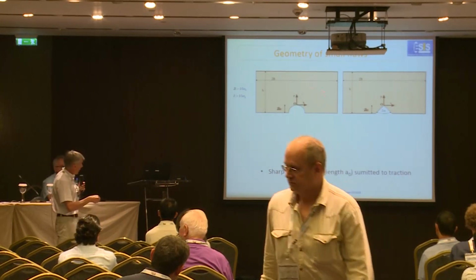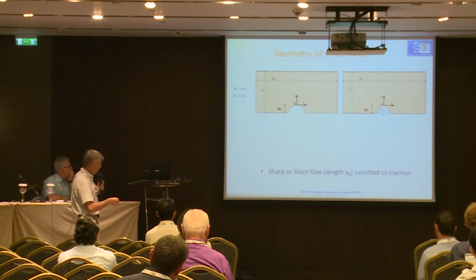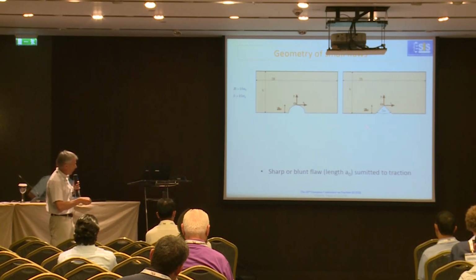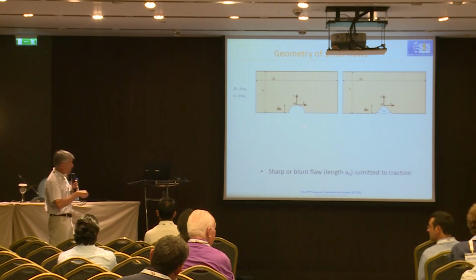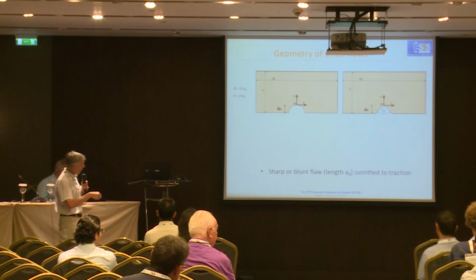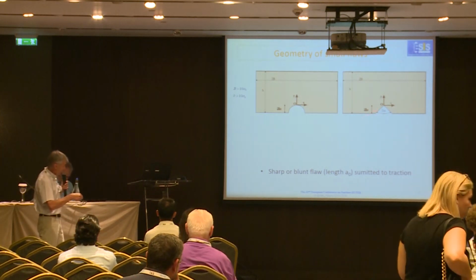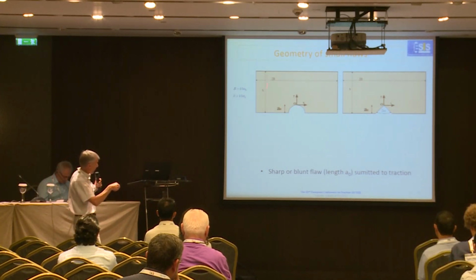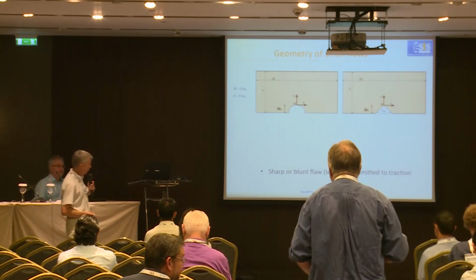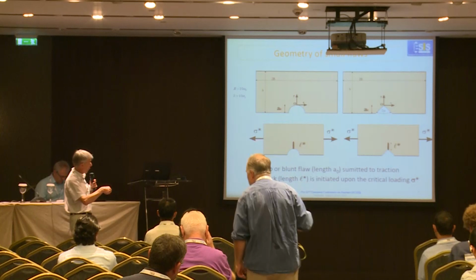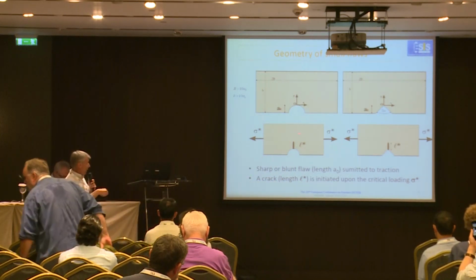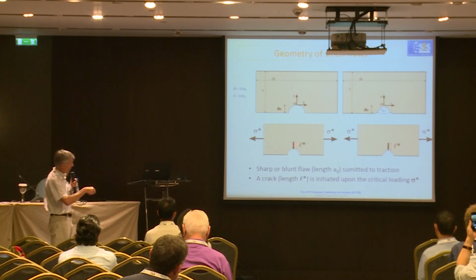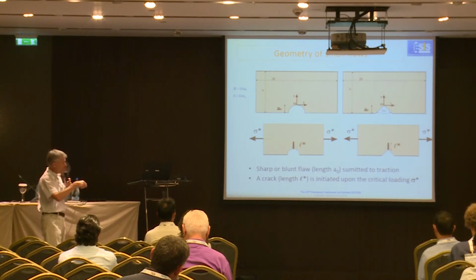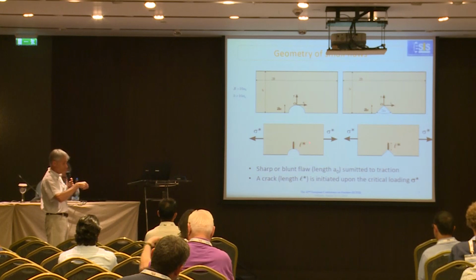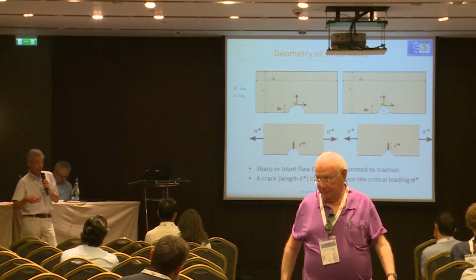For this purpose, we consider a ceramic material and a surface defect, because surface defects are known to be the most critical ones. We consider a small half hole, which we call the blunt defect, and a V-notch defect, which we call a sharp defect. The size of the defect is quite small compared to the size of the specimen. If you apply a tensile load, a small crack initiates in the vicinity of the flaw. This is mode 1, so the crack is unstable, and once the small crack has initiated, the specimen fails.